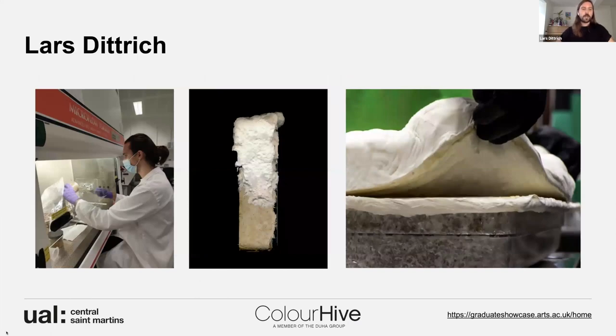So having done this early mycelium experimentation, I dug a bit deeper, and through conversations with two scientists from the Free University in Brussels, I learned about pure mycelium foam. In theory, the process of growing the material is quite simple. You take the substrate, basically what I did in the beginning, and you put it into a growth chamber that can create conditions of high humidity, high CO2, and temperatures around 30 degrees.